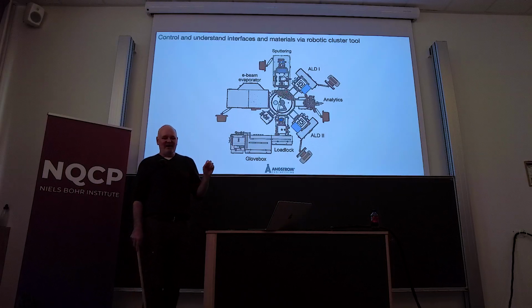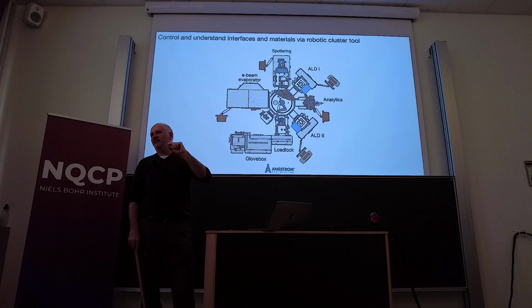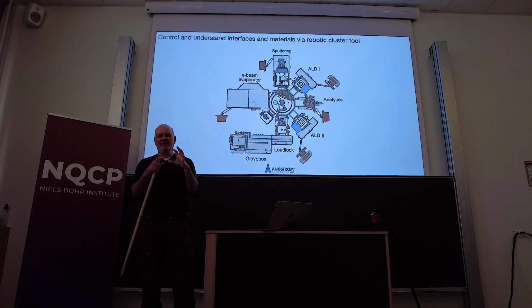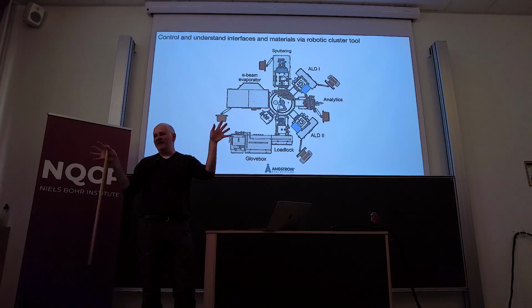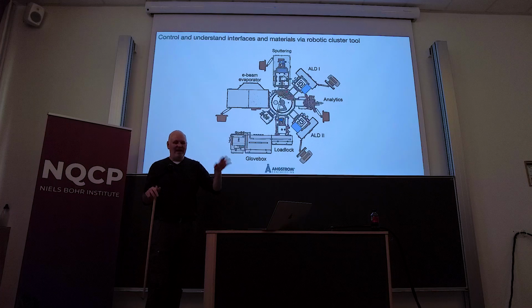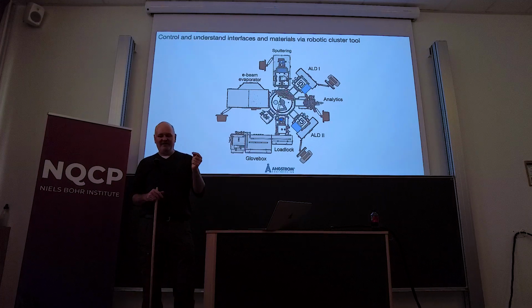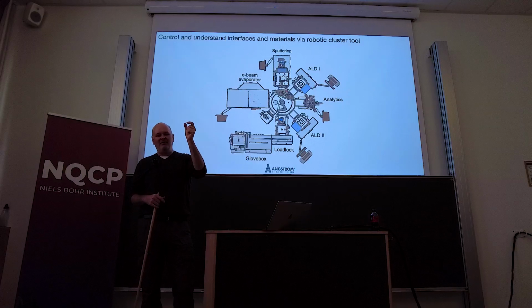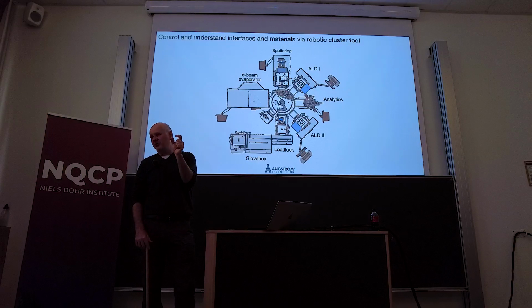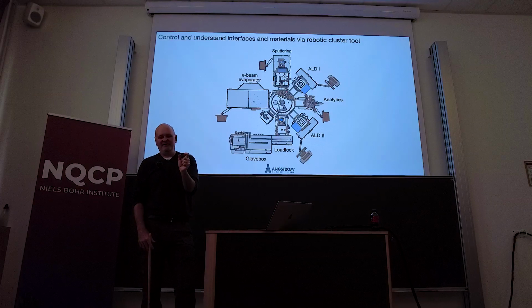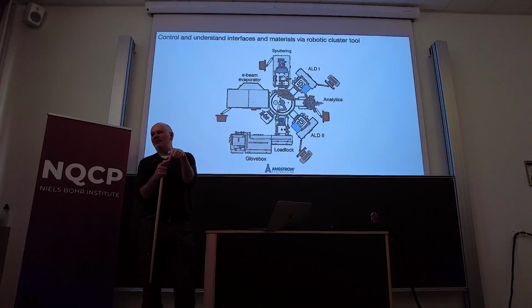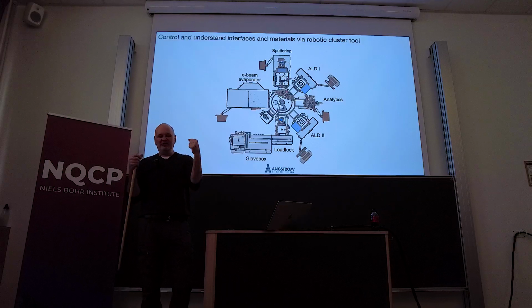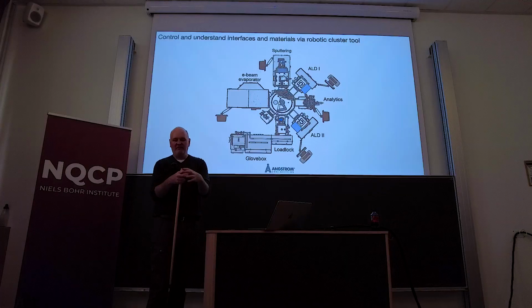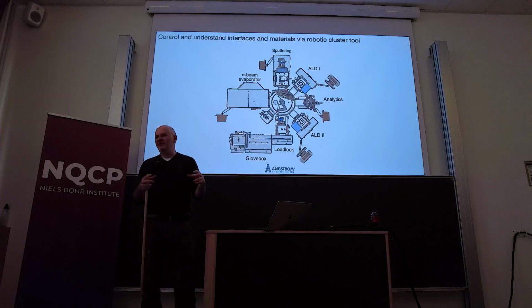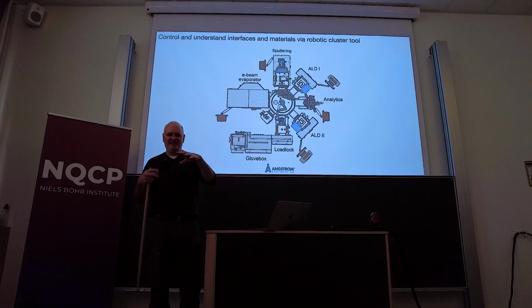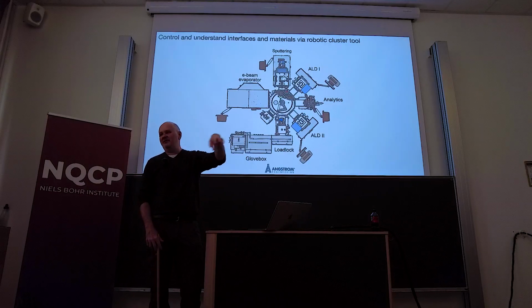So the reason is because ALD happens through metal organic precursors, gas phase metal organic precursors. So you can imagine a metal at the core and then big fuzzy organic things hanging off of them. And ALD is a completely self-limiting process, which means that you have these things bouncing around in a chamber, and when they hit essentially an OH group sitting on the surface, oxygen sitting on the surface, they will react, but they'll only pop off one of these organic things. And so when you expose the surface, you essentially will make, I'll say, self-assembled. It's not really assembled. It's randomly oriented attachments on the surface, and you can imagine fuzzy golf balls covering a surface.